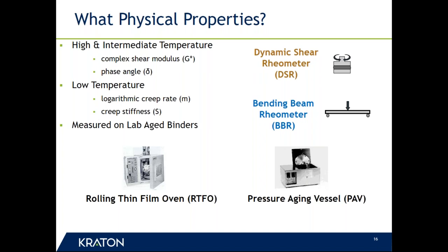The test that's used for low temperature cracking is the bending beam rheometer, and many, many other types of materials use beam fatigue or beam testing in order to characterize properties. Simply, what this is doing is, at low temperatures, you're providing a load in the middle to a simply loaded beam, and you're measuring the amount of deformation as that load is applied, and using what comes from that as a means of characterizing the properties of the material. The rolling thin film oven on the lower left and the pressure aging vessel, as I mentioned before, are there to age the binders to simulate conditions that take place in the field after plant mixing and then after aging.